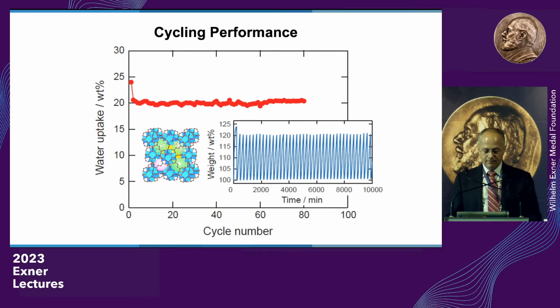Okay, so then what we did is we cycled to show that in fact water can go in and out. And you can see here about 80 cycles. And we noticed that after the first cycle, there's a slight drop in capacity, and then there's stabilization. And so we wanted to look into why we have this drop.